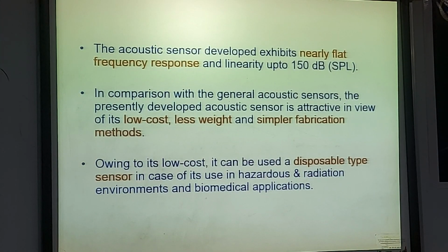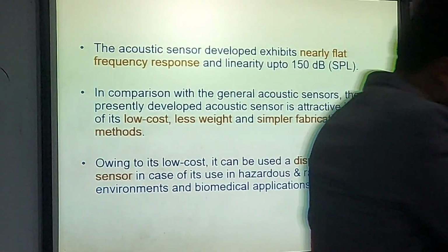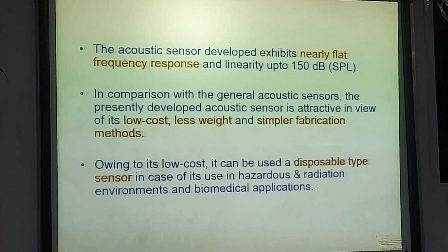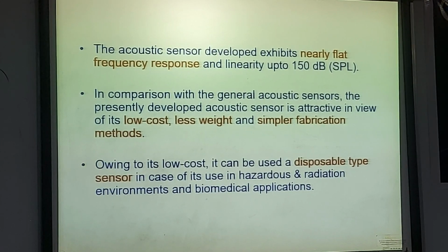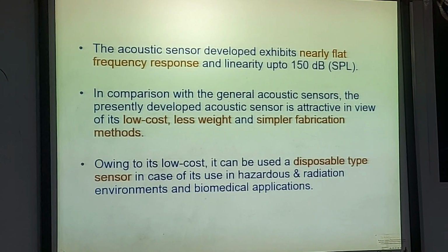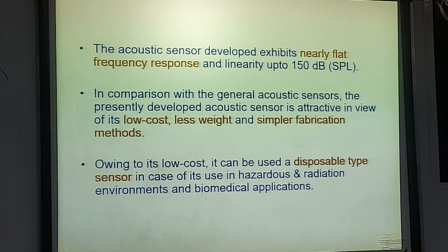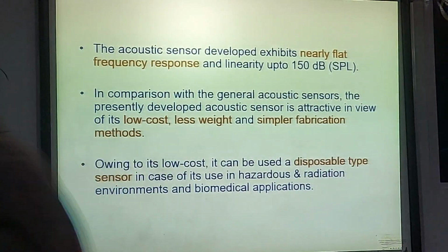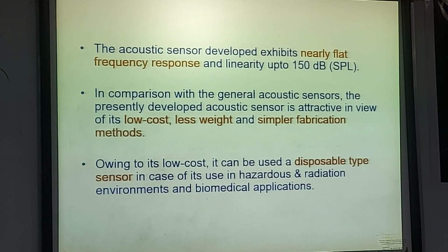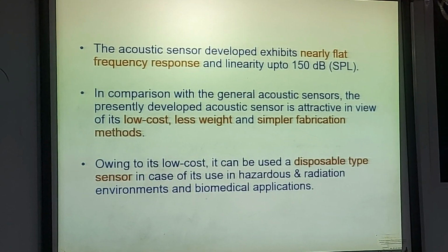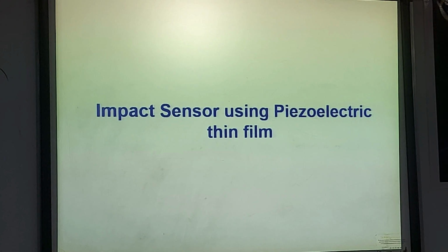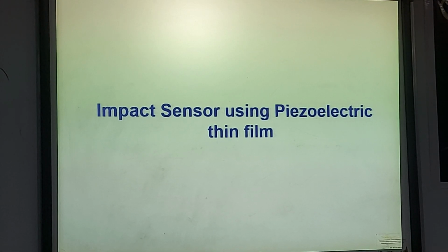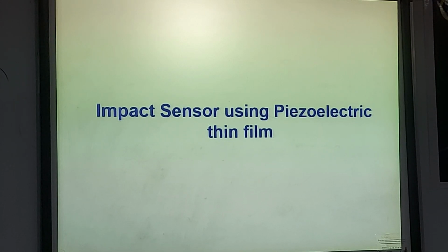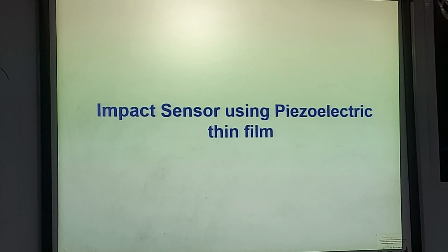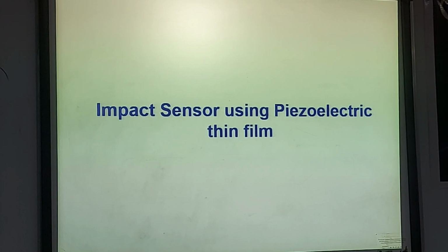So the acoustic sensor developed exhibits nearly flat frequency response and linearity up to 150 dB sound pressure level. In comparison with the general acoustic sensor, the presently developed acoustic sensor is attractive in view of low cost, less weight, and simpler fabrication methods. While it is low cost, it can be used as a disposable type sensor in case of its use in hazardous and radiation environments, as well as in biomedical applications. In fact, the same kind of piezoelectric thin film, if we use on a silicon substrate, we can make a MEMS-based acoustic sensor, which is very much there in the market.